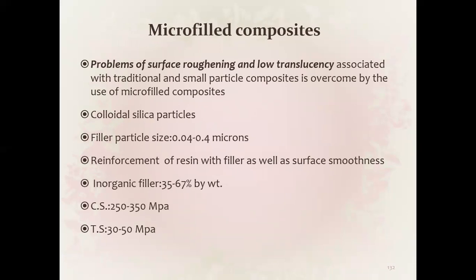Problems of surface roughening and low translucency associated with traditional and small particle composites are overcome by microfill composites. Colloidal silica particles — filler particle size 0.04 to 0.4 microns — reinforce the resin with improved surface smoothness. Inorganic fillers: 35 to 67 percent by weight. Compressive strength 250 to 350 MPa, tensile strength 30 to 50 MPa.